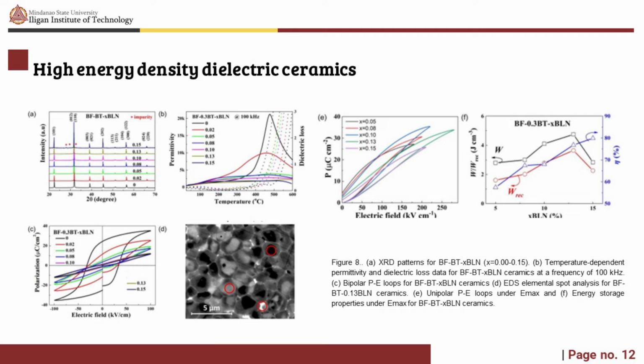Figure 8e and figure S9 in the electronic supplementary information show the unipolar PE loops of BF-BT-xBLN, where x is greater than or equal to 0.05 and less than or equal to 0.15, under Emax, with maximum polarization and change in polarization and Emax values presented in figure S10 in the electronic supplementary information. The maximum polarization and the change in polarization rise linearly with the increasing electric field, with a slight improvement in Pr, as can be seen in figure S10.